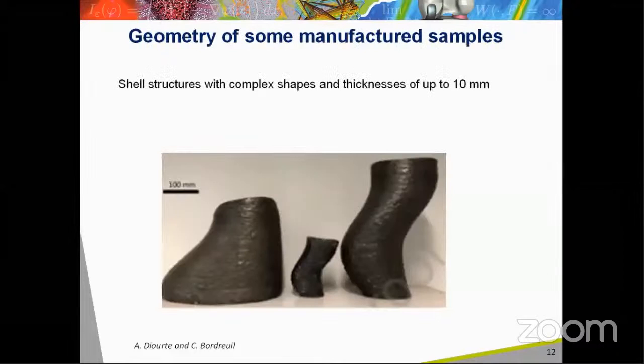In this picture, one can see some examples of components for which the WAAM process is of interest. These kind of shell shapes are difficult to obtain with conventional processes or rather costly. So the WAAM process is a convenient process for manufacturing shell structure with complex shapes, having a thickness up to about 10 millimeters, which is the maximal thickness of the layers that can be deposited with this process.